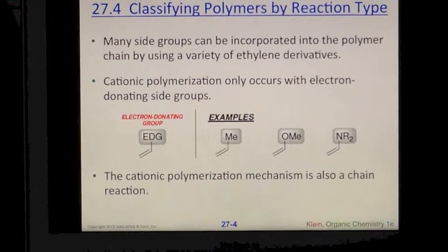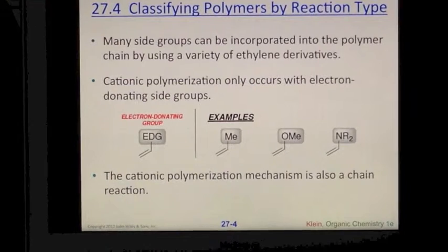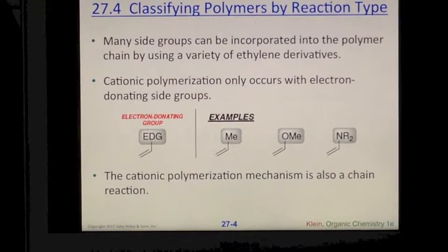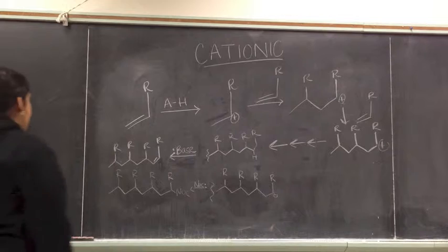The acid catalyst most often used is formed by treating BF3 with water. The carbocation generated during the initiation stage is then attacked by another monomer in a propagation step, and the process repeats itself, enabling the polymer chain to grow. The function of the electron donating group is to stabilize the carbocation intermediate that is formed after the addition of each monomer to the growing polymer chain.